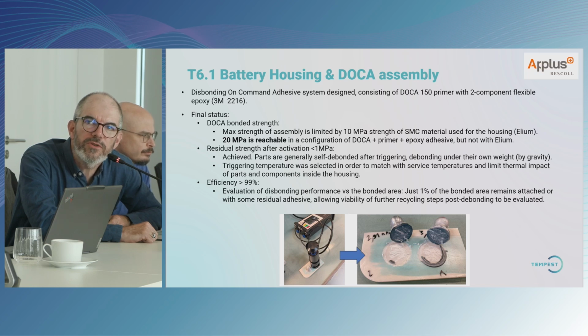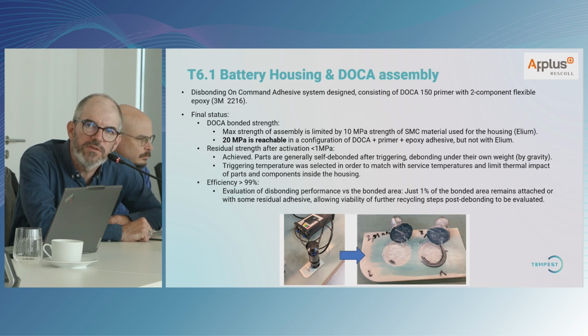And the temperature was selected to match the maximum service temperature of the system, which was in the range of 80-85 degrees C, and to keep some safety gap in order to avoid any unanticipated and unwanted debonding. But in the end, the final strength after debonding was very low, and this strength was evaluated by just manual separation after cutting the parts. And the debonding efficiency was above 99% because we have very limited areas still sticking.